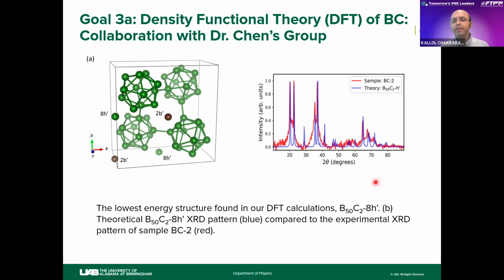The right panel is the X-ray diffraction pattern. The red curve is the experimental pattern, the blue curve is the theoretical pattern, and as you can see, they match very well between experiment and theory. So we can definitely say that our synthesized coating is B50C2 type coating.